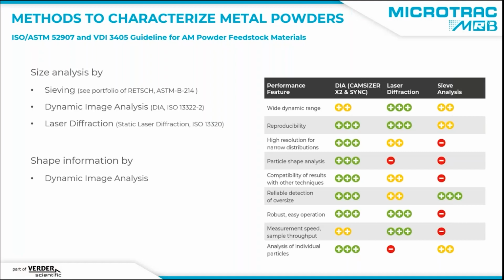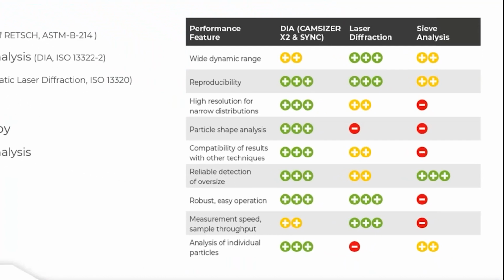So when we look at the different methods, we can see that the methods have advantages and disadvantages. For example, when we look at the width of the dynamic range of the particles, we have small particles and large particles. If the small particles are much smaller than the big particles, then laser diffraction is the method of choice. The sieving and CAMSIZER cannot measure such a wide range of particle sizes. However, for additive manufacturing, particle size range is typically from 5 to 45 microns, or maybe 5 to 150 microns. And in this range, all the different methods provide good results.